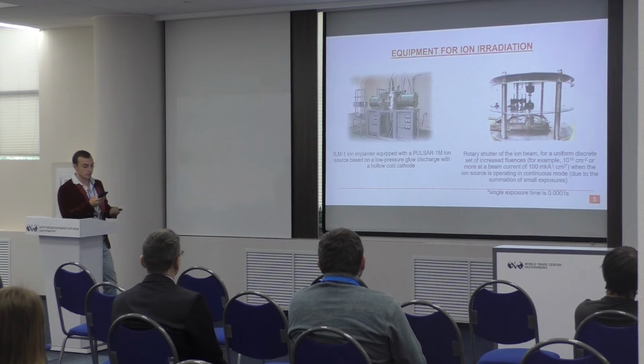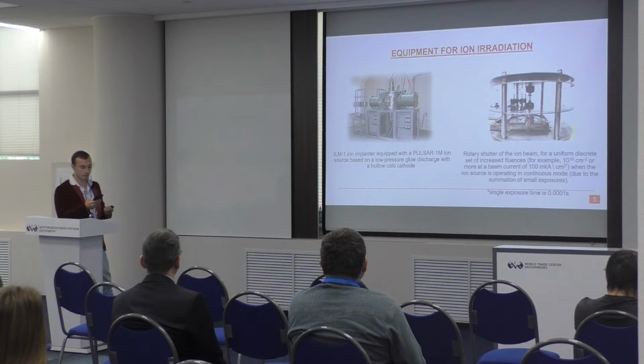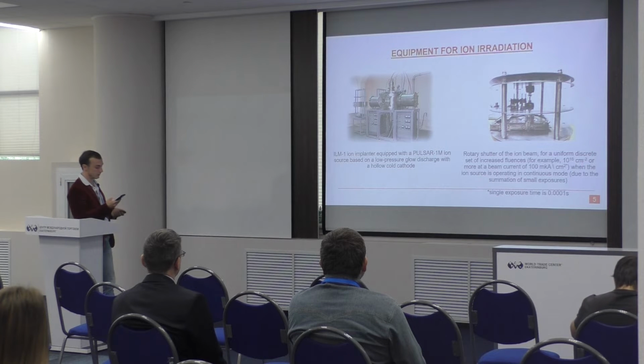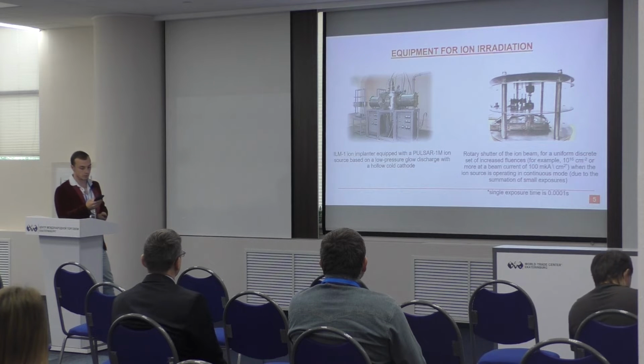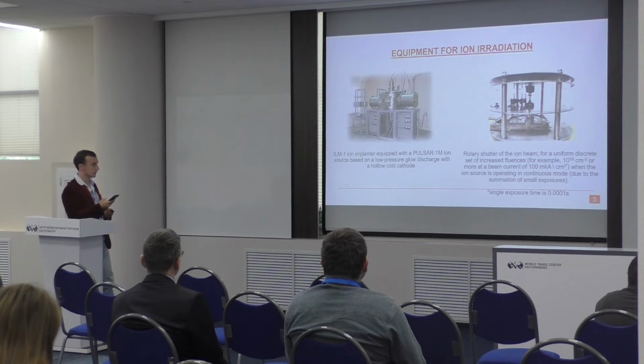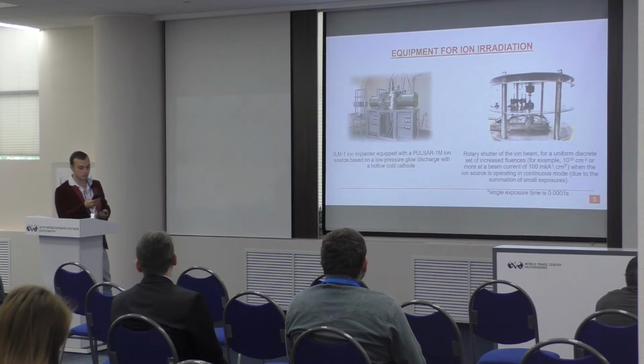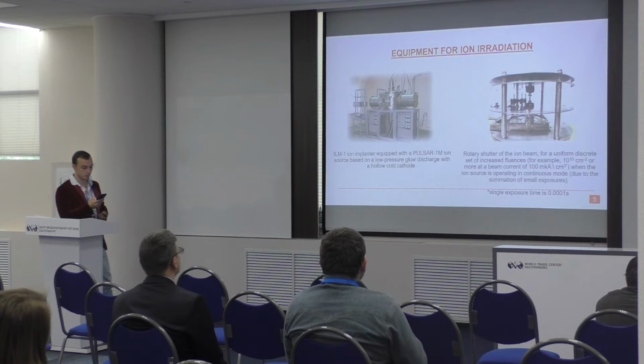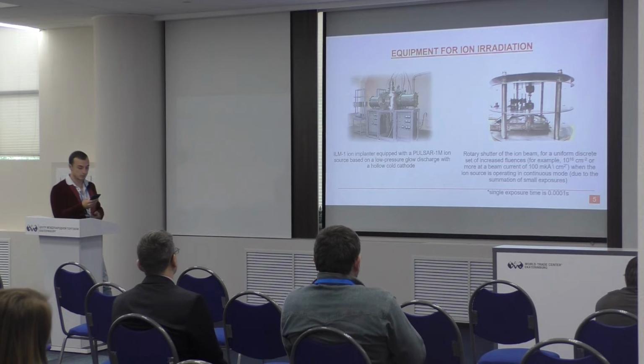ion source based on a low pressure glow discharge with a hollow cold cathode. During irradiation of the superlattices, the same beam parameters were used. The ion energy was 10 kiloelectron volts, the ion current density was 100 microamperes per square centimeter. Fluences were chosen starting from 10^14 cm^-2.